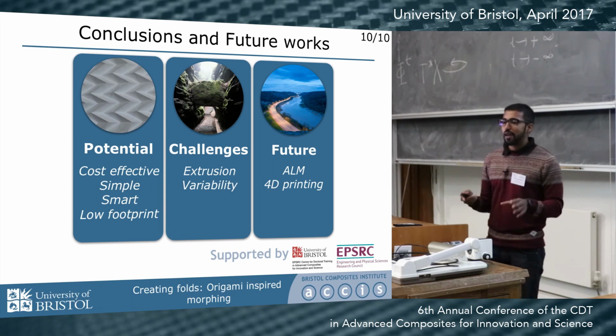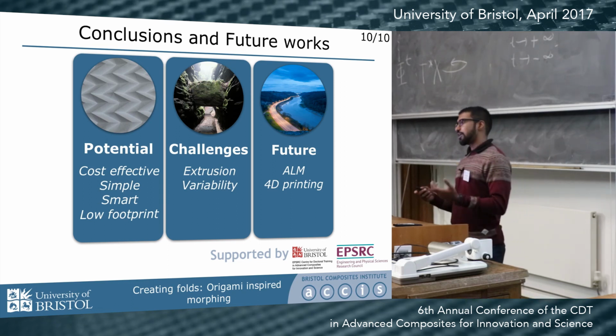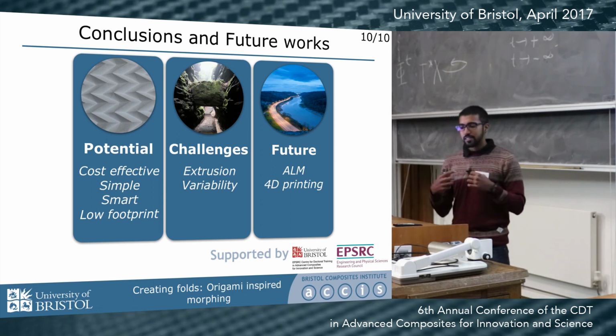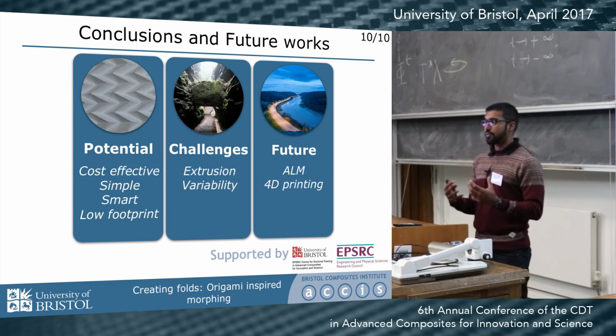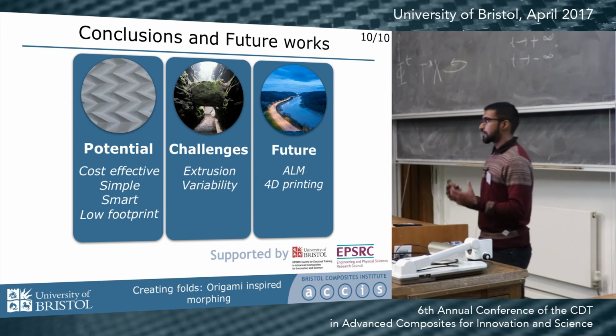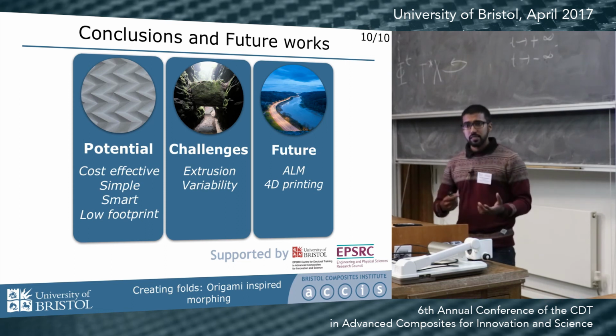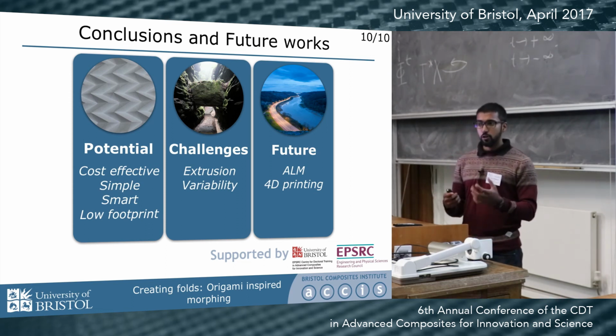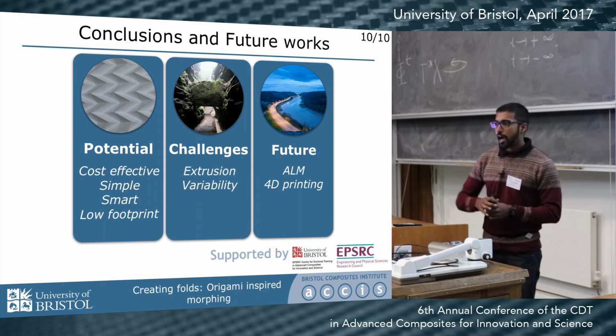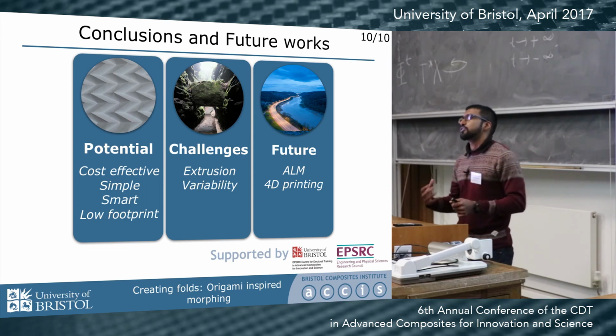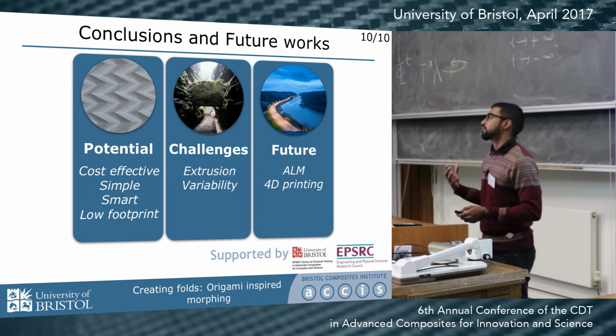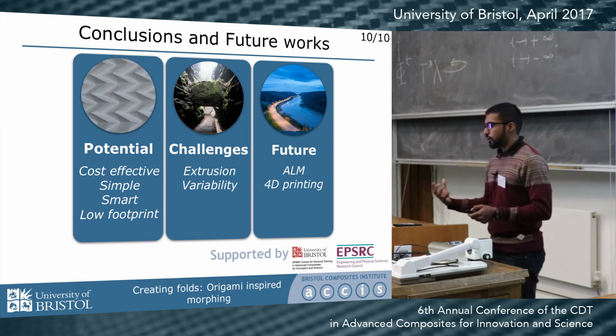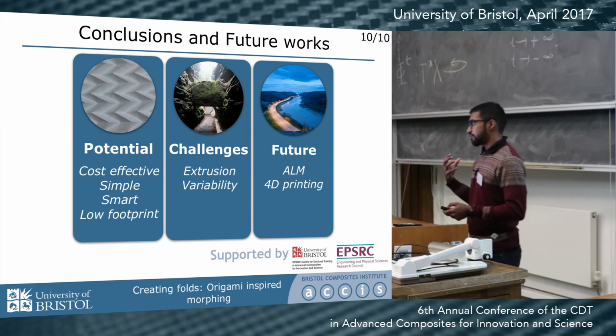Due to the nature of manual extrusion and inherent variability within paper, the standard deviation between samples is rather high at this stage for in-depth characterization. This can be mitigated by adopting a controlled dispensing system for the hydrogel and also integrating cellulose into the landscape of additive manufacturing methods to enable 4D printing of this material.